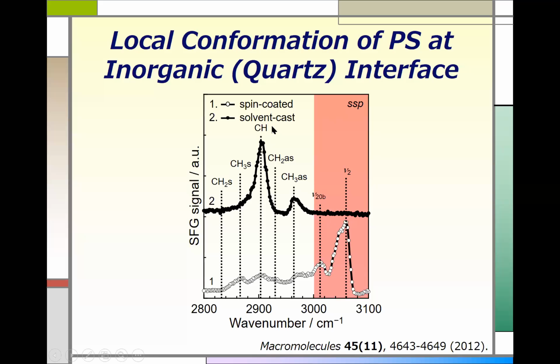So imagine the following. In case of the spin coating method, the substrate is going to be rotated. So polymer solutions must feel centrifugal force. In that case, polymer chains must be aligned in the plane. And phenyl groups are directly attached to polymer chains. So as I told you, polymer chains are aligned in plane. That is why we could see this kind of orientation of phenyl groups, side chains, at the interface.